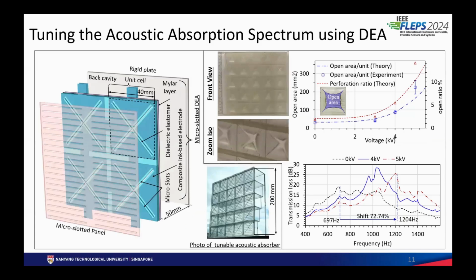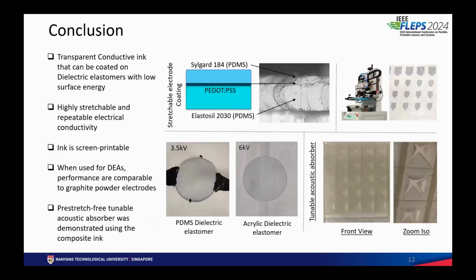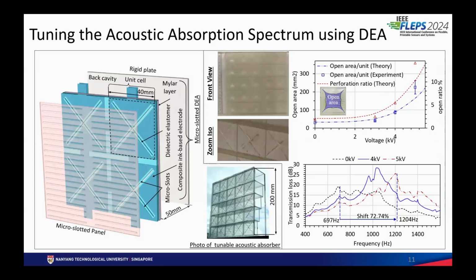And this is the final form of the acoustic absorber. The final acoustic absorber consists of a front microperforated panel, the blue one, behind which is the bending dielectric elastomer actuator made with the screen printed or blade casted electrode, and there is a back cavity, which in combination forms the smart acoustic absorber. And we activate the device. Let me try to play the video. Okay, so when you activate the device, it opens up like this. We have an array of 25 cross slots, and when we activate the device, it will open up like this. And this change in open ratio with about 5 kilovolts is almost 12%.